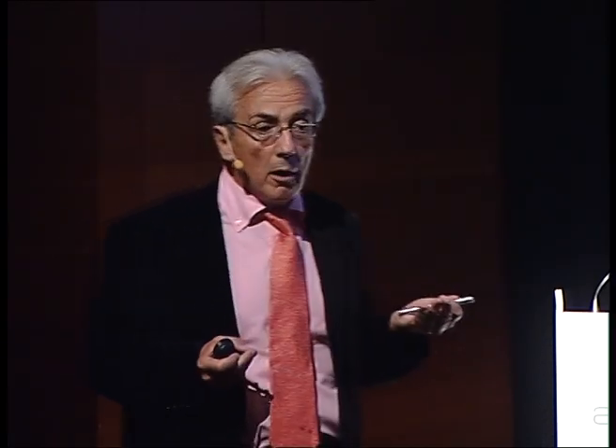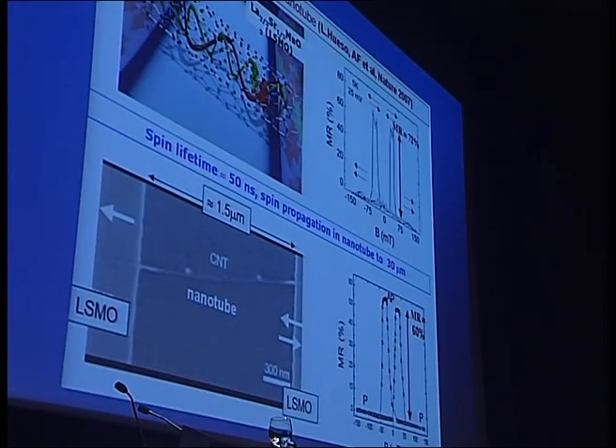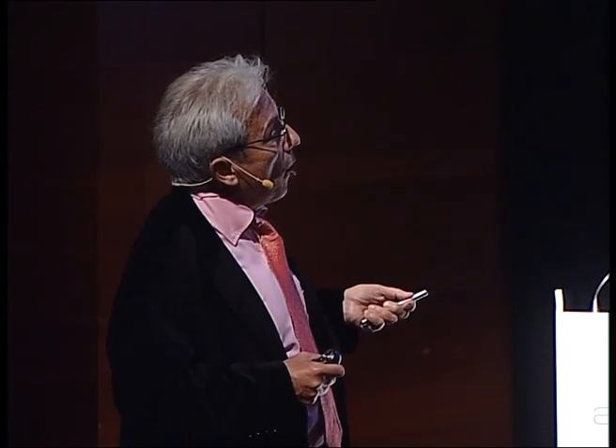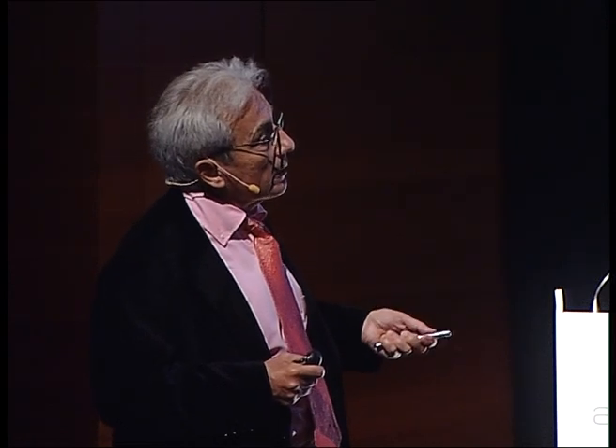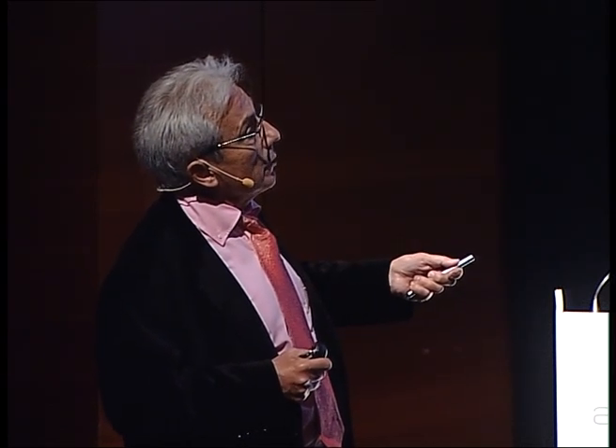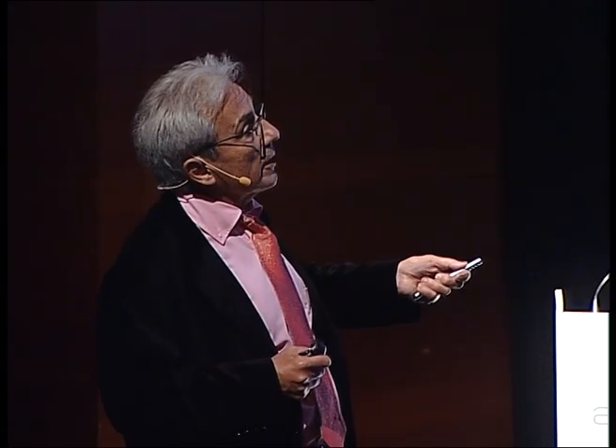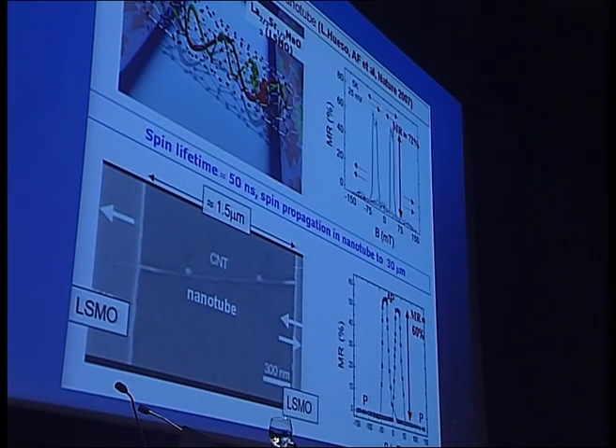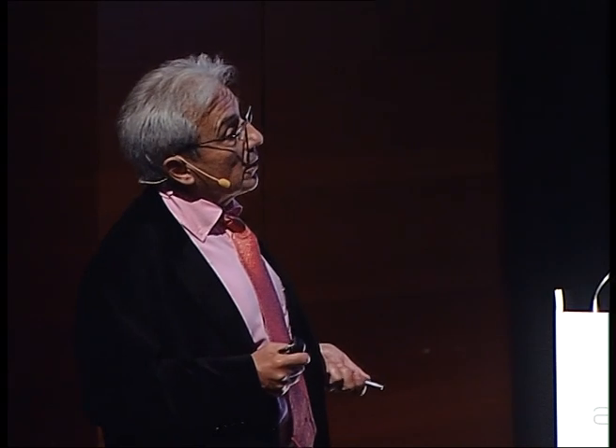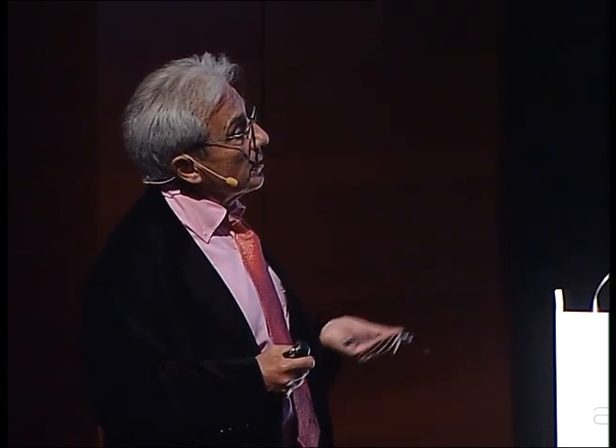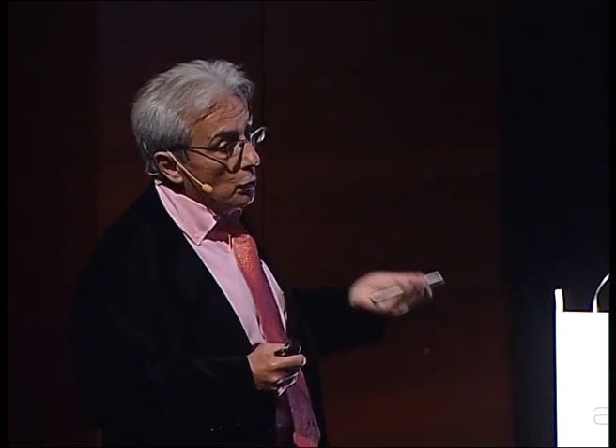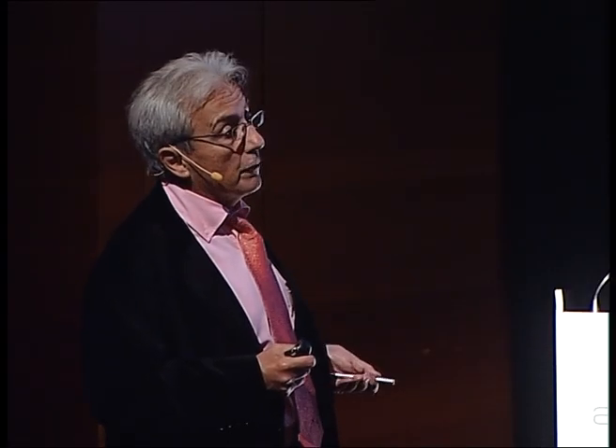But we have seen that in GMR, the distance between the two magnetic layers must be of the order of a few nanometers. And you can see that in this experiment, instead of a few nanometers, the length of the carbon nanotube can be more than 1 micron, and the GMR effect, the difference between the resistance of the anti-parallel and parallel configuration, can be very large, 60%, 62%, even if the distance is 1 micron, 2 microns. So this means that the spin can propagate to very large distance in this type of carbon-based material due to the small spin-orbit coupling and to the large velocity of the electrons.